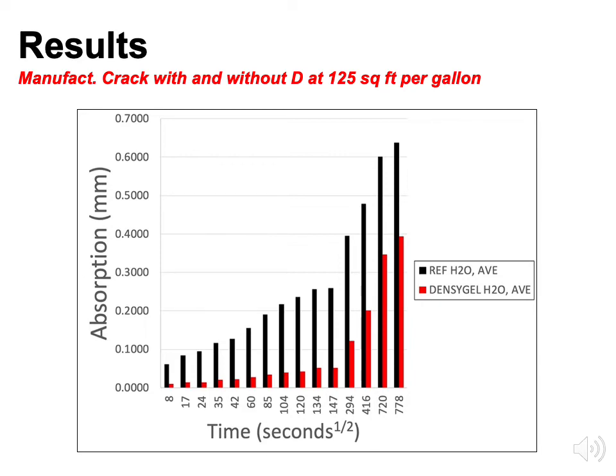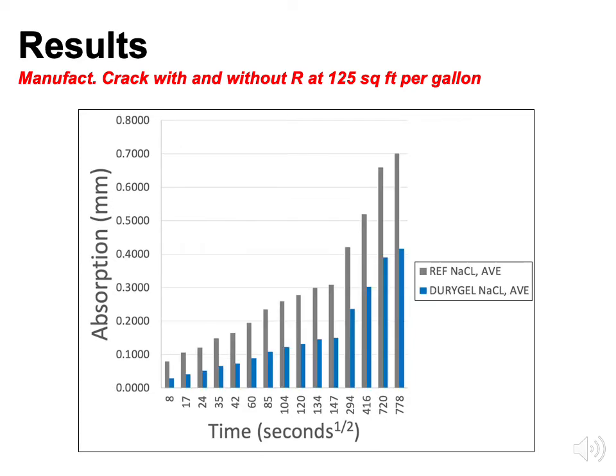We ran another set of samples using the DuryGel, but in lieu of using just potable water, we used a sodium chloride solution at 8% solids. The reason why we did that is oftentimes when we go out to the field and we see concrete cracks, those concrete cracks aren't clean and free of chlorides or sulfates. They're actually pretty much inundated, as we see in our cruise tunnel job site, with a significant amount of salt. And as you'll see in the next few days, we'll be sending out